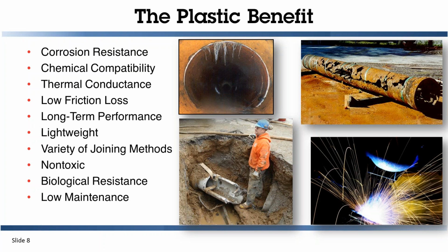Because of the relative chemical inertness and minimal effects of internal and external corrosion, there is very little change in the physical characteristics of plastic piping over dozens of years. Examinations of pipe samples taken from some systems have shown no measurable degradation after 25 years of service. Most thermoplastic systems can be designed for a useful life of 50 years and sometimes much longer.